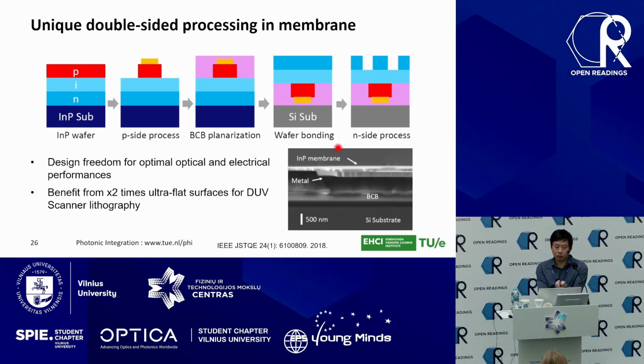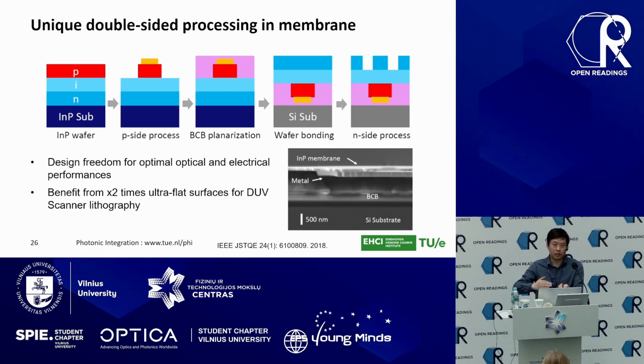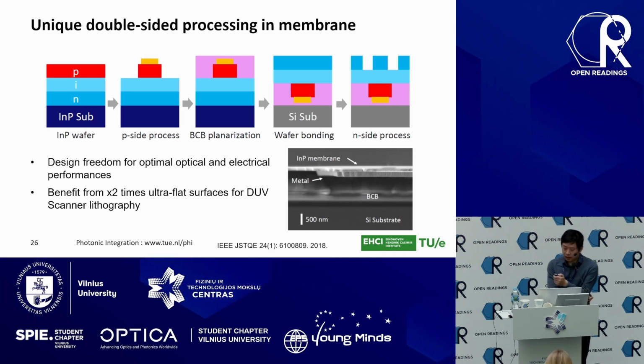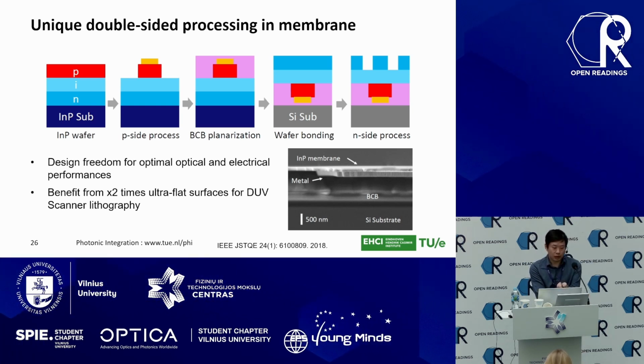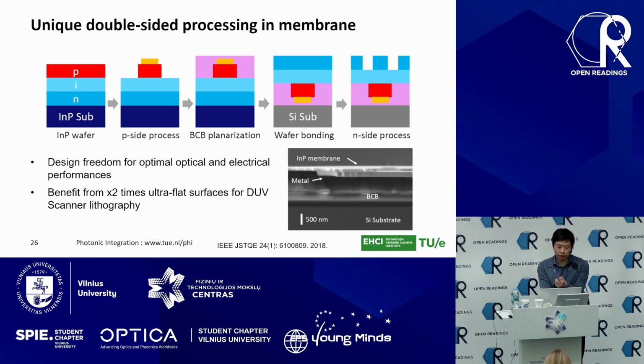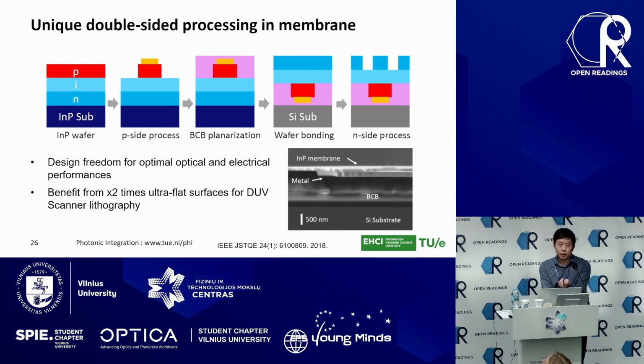And at this step, you can see that we can create mesostructures and metal structures buried inside my membrane. One benefit, as I mentioned, is that we have an extra degree of freedom to design its optical and electrical properties. Especially, it's very beneficial in optimizing the RC constants of the diodes. Another benefit is that the wafer can expose ultra-flat surfaces: one at the beginning, and the second time after my substrate removal. So I can achieve two ultra-flat surfaces, which are extremely important if you want high-resolution lithography. On the bottom right, you see an example of the double-sided processing. You can see that we have a metal flipped on the backside of the membrane and buried inside my bonding layer.